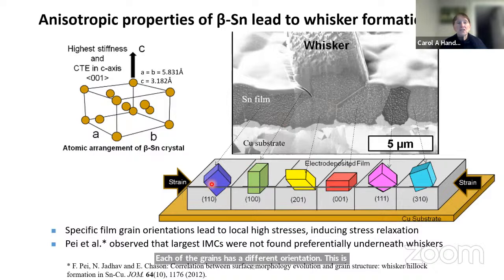This is a representation of a tin crystal. This is the unit cell. So it's a body-centered tetragonal structure, a squashed structure. So you can see each of the grains has a different orientation, and they have different mechanical behavior also. So when you strain them, the grains have different responses, even just to the elastic component of the strain, and so these also enter in as well.